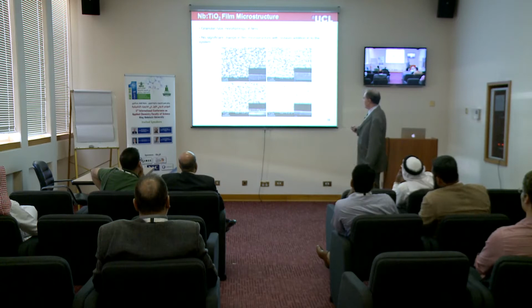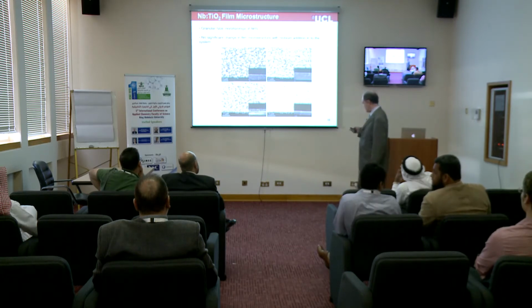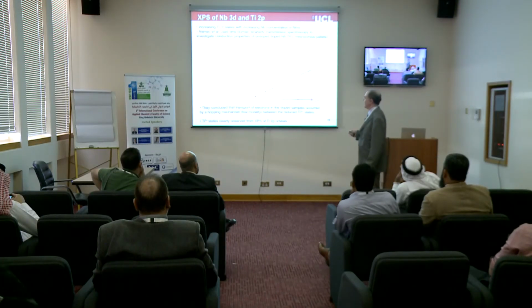When we look at the electric properties of the film, again they've got this nice microstructure, which is what you need for a solar cell application, and we can get down to about 6 ohms per square, which is better than the commercial product, which is around 10. Very unusually for this system, when we do the doping, we found that it's the titanium that gets reduced.